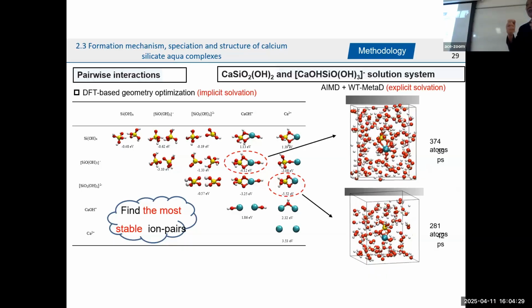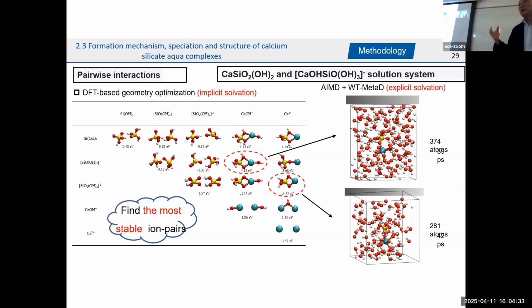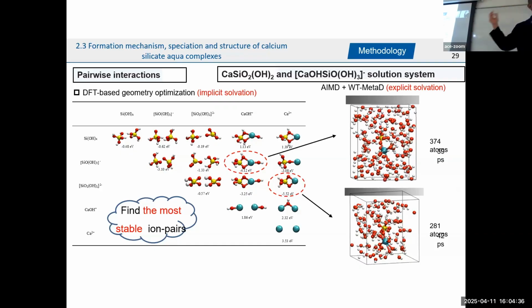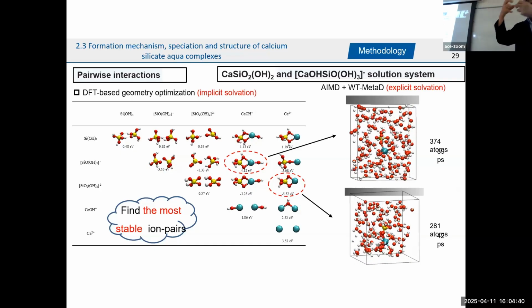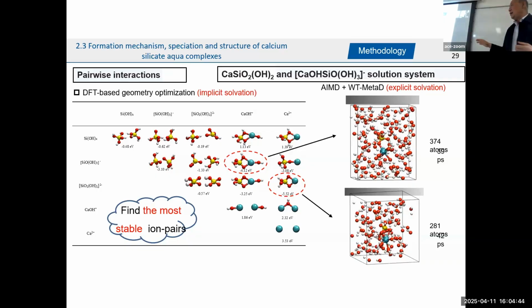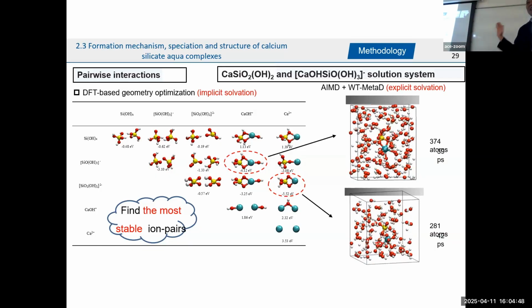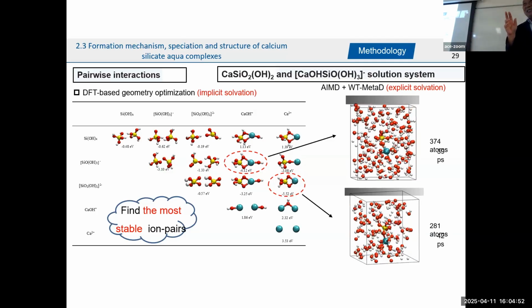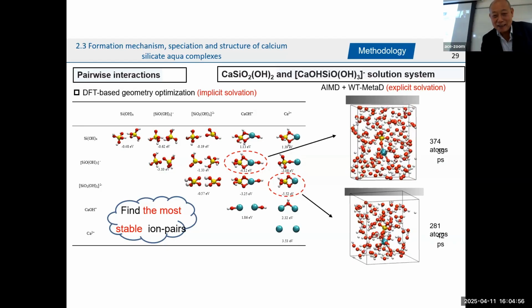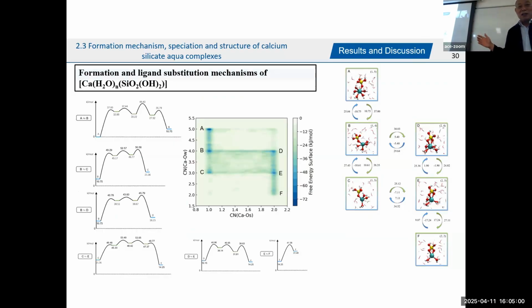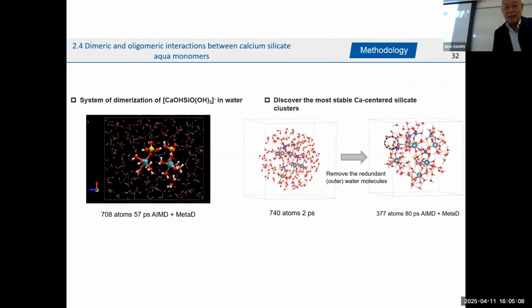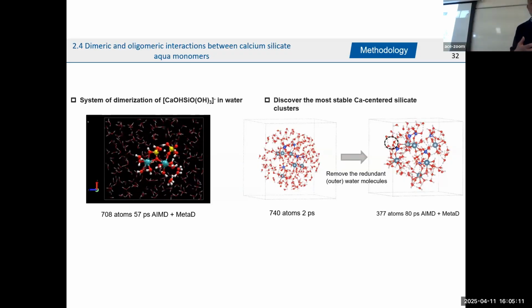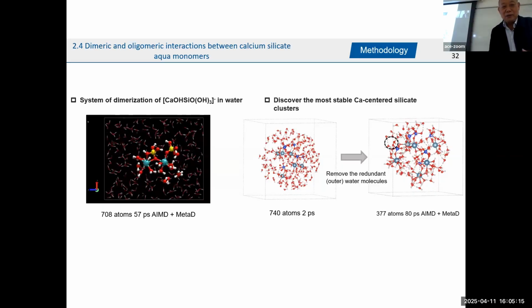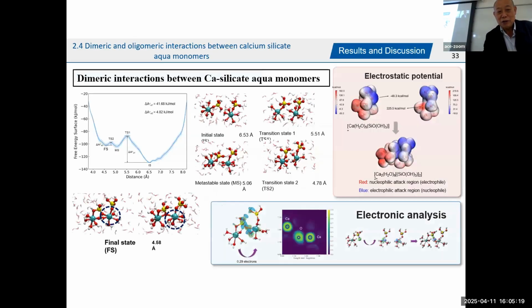We know that we have the so-called secondary formation of CSH, the pozzolanic reaction. In that case, that's exactly like this. So you have an assembly of calcium and silicate. I said your work is also good, but not really for the CSH formation on the surface. So he did this, and he also found two very stable combinations of calcium and silicate, and they continue to join together to form so-called secondary CSH.